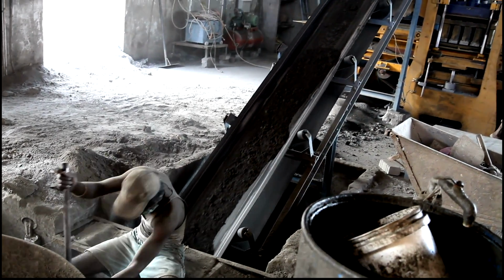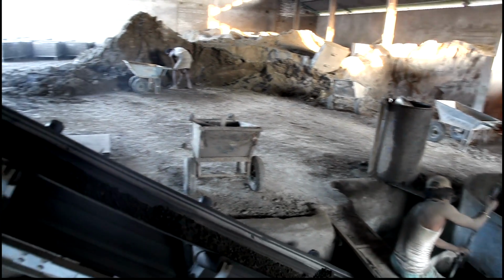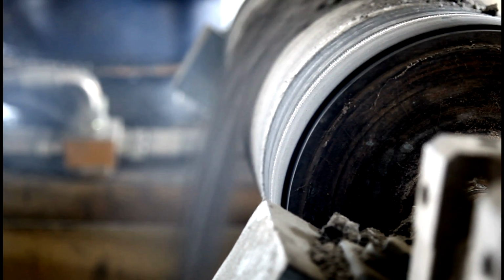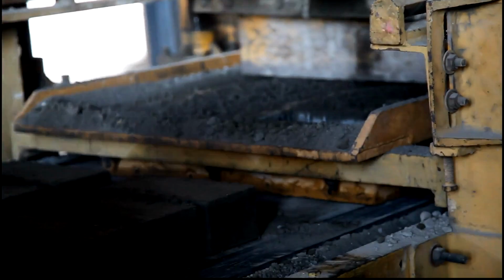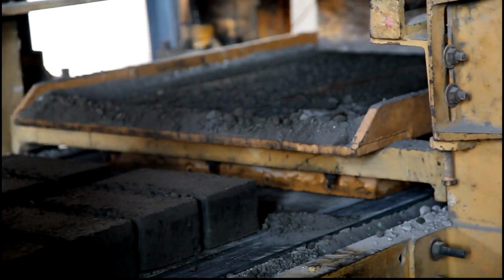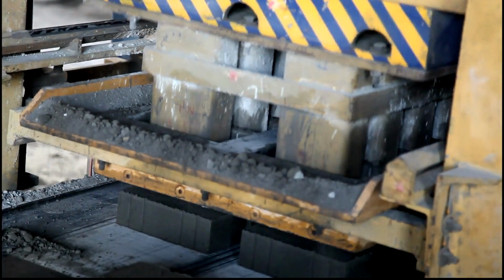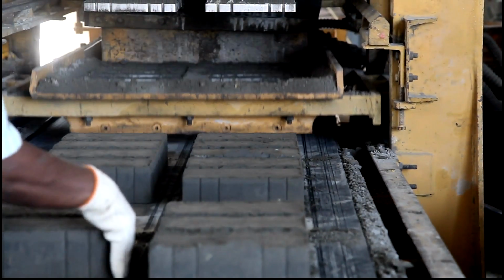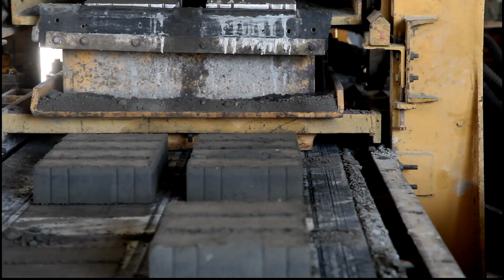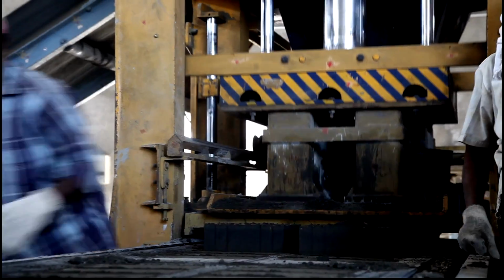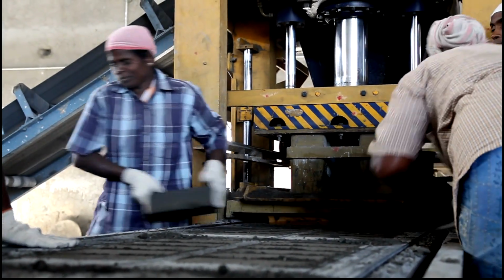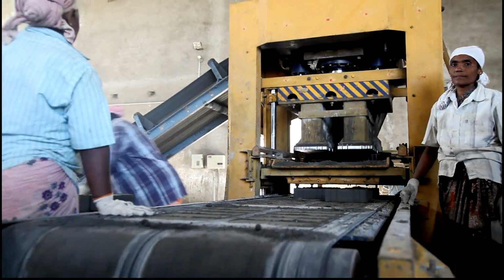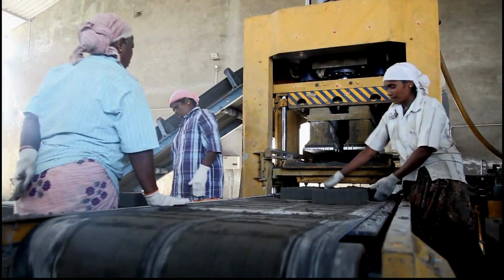Properly mixed raw material is generally transported through a belt conveyor to the press feed hopper. The mix is then fed to the hydraulic rotary press, where the molds are automatically filled. A set of 3 molds, each located 120 degrees apart, sits on the rotary table. Bricks are formed at a pressure of 150 to 200 kilograms per square centimeter. In the case of a vibro press, the mix is manually brought from the pan mixer and then filled in molds. The table on which the molds are kept is vibrated. Generally, bricks made from both presses are of acceptable quality.